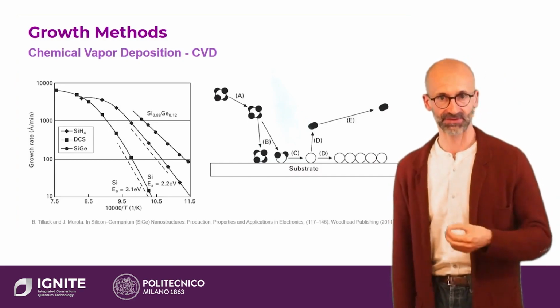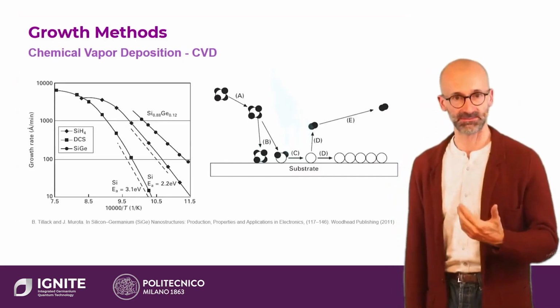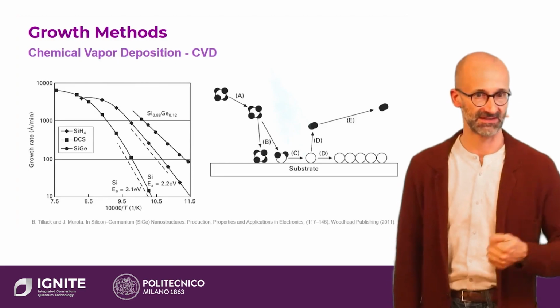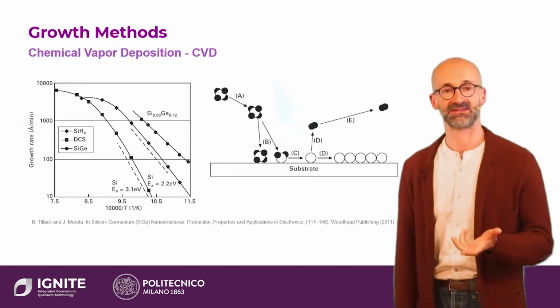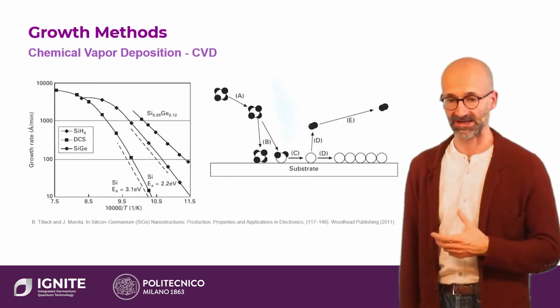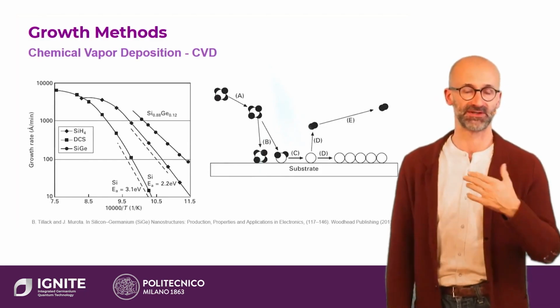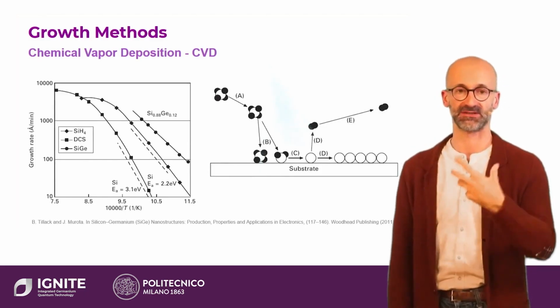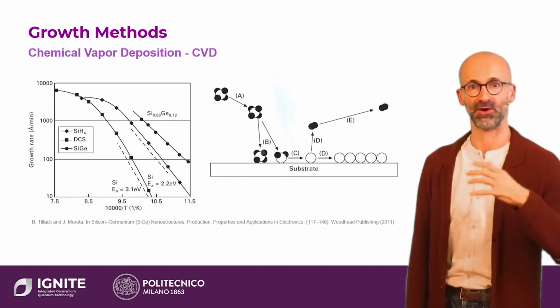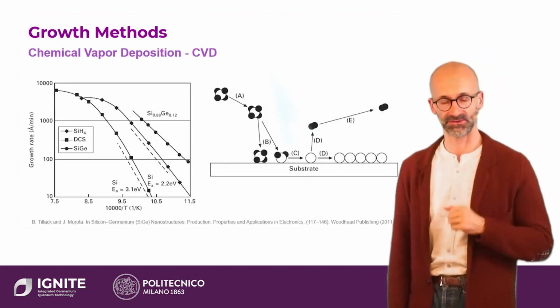So this means two things. Firstly, that the growth rate is strongly dependent on the substrate temperature. In fact, as you can see, it's exponentially activated by the substrate temperature, mainly because you need free sites on the substrate, so you need hydrogen to desorb from the substrate to allow a chemical bond to be exposed for one of the precursor molecules to attach.